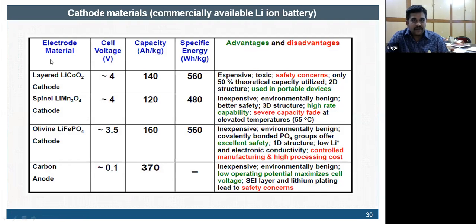Okay. So this is the overall comparison of lithium cobalt oxide, spinel, lithium iron phosphate, and carbon. As I mentioned a couple of slides back, the advantage of cobalt oxide is, okay, fine, 560 watt-hour per kg energy density, higher than spinel, but the problem is toxicity and safety issues. So the alternative has slightly lesser energy density as well as capacity, but the advantage is that it is inexpensive, cheaper.